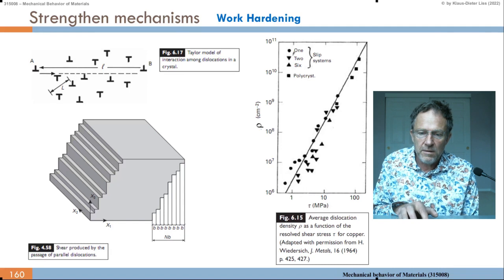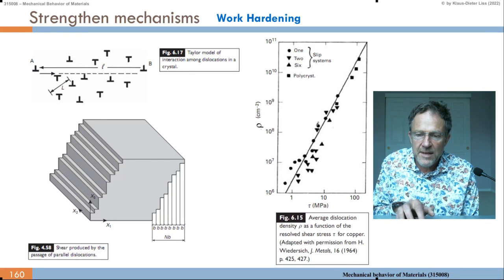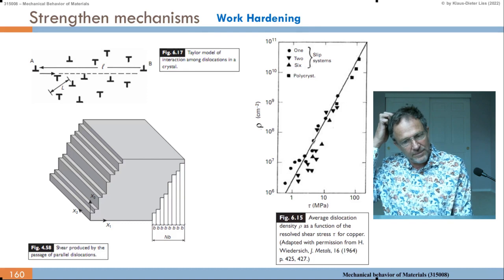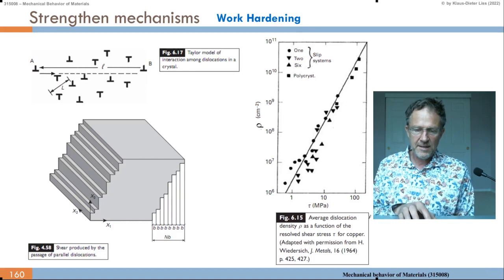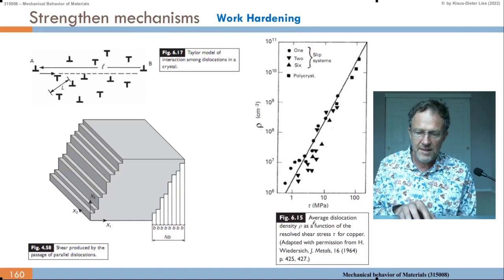So also it depends how many slip systems we have. Just for 1 slip system, we get the round points here. There's 1, there. Then 2 slip systems, triangles to the bottom. 6 slip systems, triangles to the top. And polycrystalline materials, we have these squares here. So this is an average dislocation density as a function of resolved shear stress for copper.